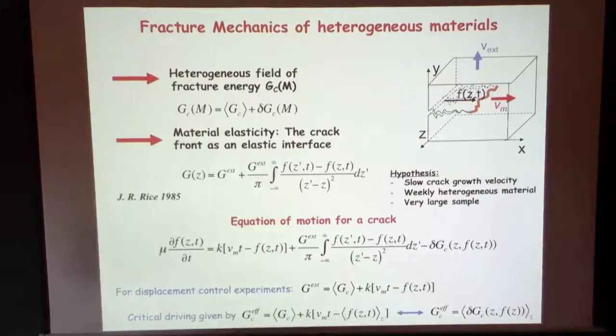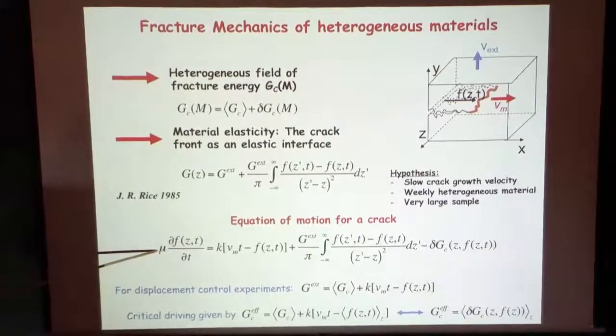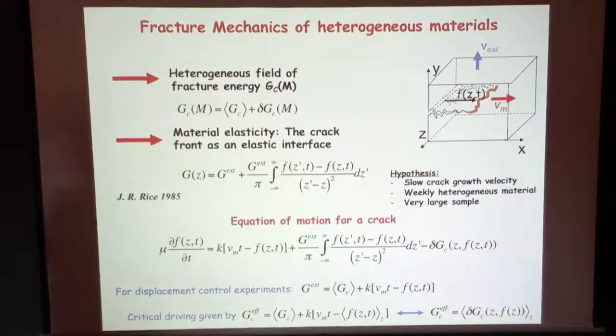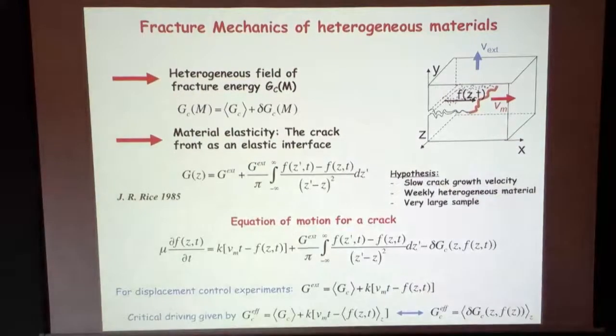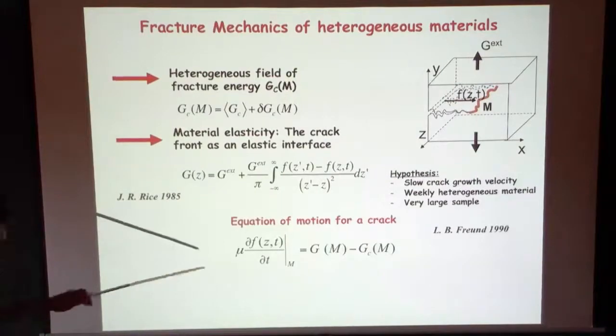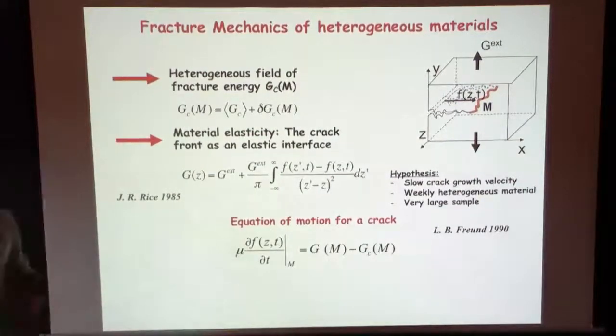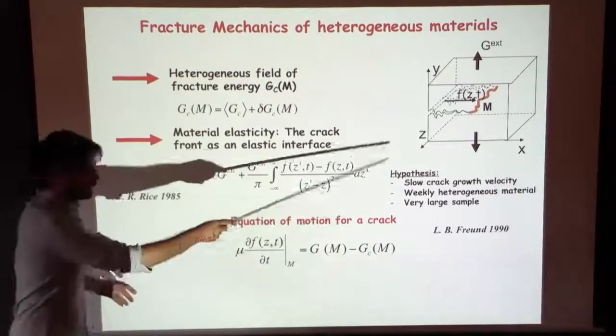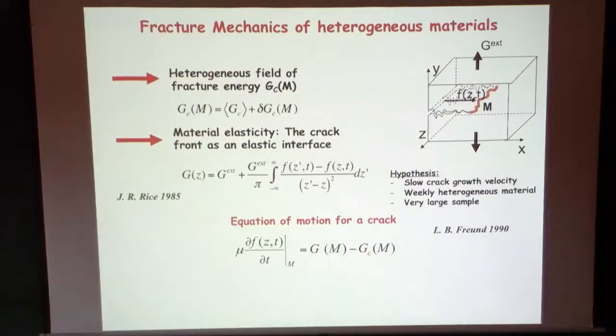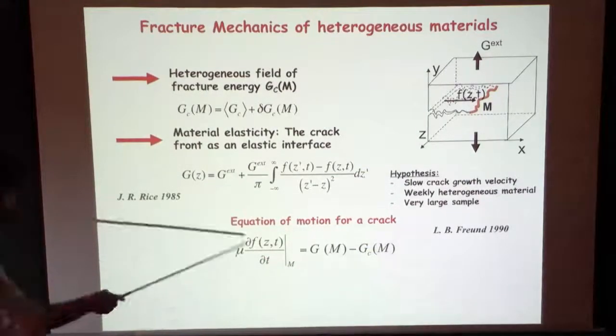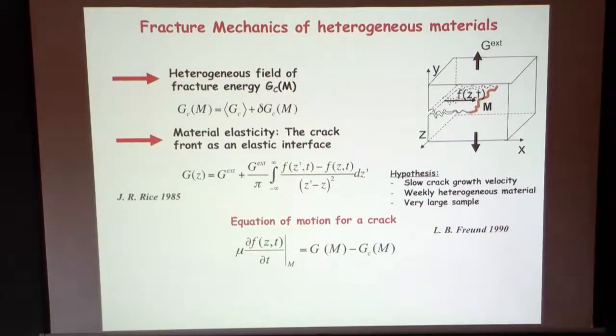It's a good point. It's setting a time scale, but it's the time scale at which you move from one metastable state to another. If you are quasi-static, the final metastable state does not depend on mu. So that's why it's sort of okay that it doesn't depend on Z, because you don't really care about it. Actually, if we believe that the elastodynamic theory works, you can calculate this mu, and it's related to the velocity of sound in your material. But when you look at this value, it doesn't seem very reasonable. From an experimental point of view, it's kind of an effective mobility. It's not so clear right now, but we are lucky it doesn't affect the results so much.